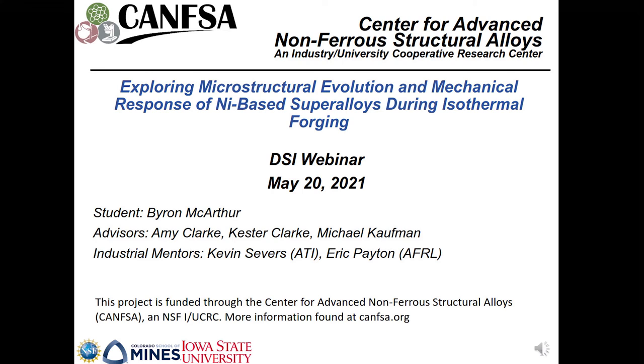During the subsequent isothermal forging, you have the dissolution at that temperature, about 1100 Celsius or so, plus or minus 10 or 20 Celsius. You're having all of the secondary gamma prime dissolved and you're doing deformation at lower strain rates to try to have a relatively superplastic deformation. So you're not having too much dislocation accumulation within the gamma. And then they're able to achieve that by having the primary gamma prime existing.